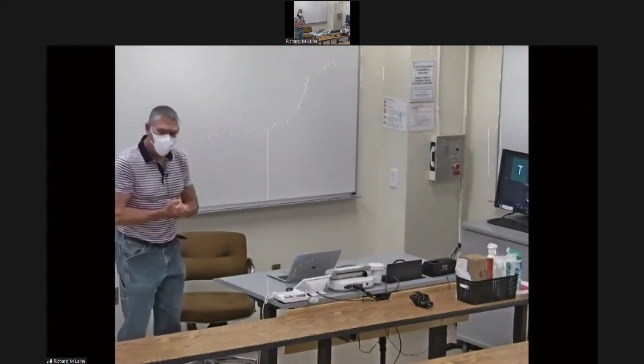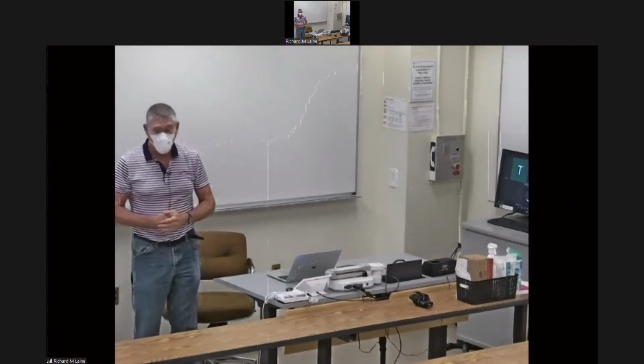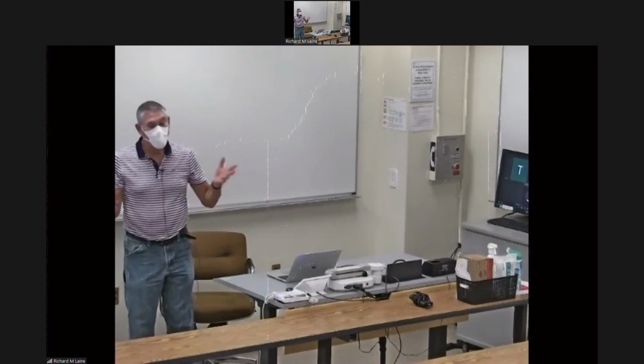And then you'll note we haven't talked about the anion being solvated. We'll come back to that, but the anion is also going to be solvated to some extent, and it's going in the other direction. As a consequence, the volume occupied by both ions is larger than just the diameter of the original ion, and the friction that these ions undergo when they move is much larger. And that then, in a sense, is generating heat, which means you're losing electrochemical potential because it's going to heat. And gosh, do you think that happens in polymers and solid electrolytes too? Yep, but in a different way.